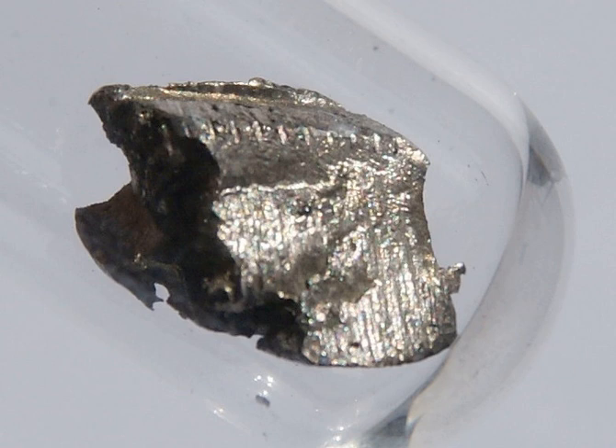Its production resulted in a large amount of lanthanides being simultaneously extracted as by-products. Applications were soon found for them, especially in the pyrophoric alloy known as mishmetal. Composed of 50% cerium, 25% lanthanum, and the remainder being the other lanthanides, that is used widely for lighter flints. Usually, iron is also added to form an alloy known as ferrocerium, also invented by von Welsbach. Due to the chemical similarities of the lanthanides, chemical separation is not usually required for their applications, such as the mixing of mishmetal into steel to improve its strength and workability, or as catalysts for the cracking of petroleum. This property of cerium saved the life of writer Primo Levi at the Auschwitz concentration camp, when he found a supply of ferrocerium alloy and bartered it for food.